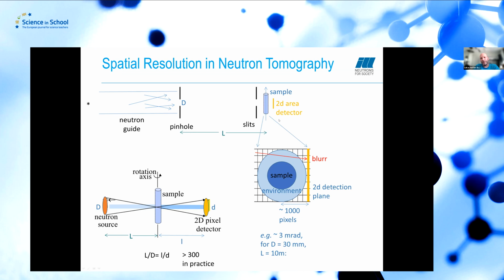And if you do tomography, you turn the sample, you have the ideal case of a cylinder. Then you can really approach the detector, the detection plane, as much as possible, if you don't have a sample environment; otherwise you need to take the distance of the sample environment into account. And let's say if you have 1,000 pixels that you want to reconstruct, then you would say, okay, I can accept something like 1 pixel of blur radius, in order not to be less resolving than the detector.